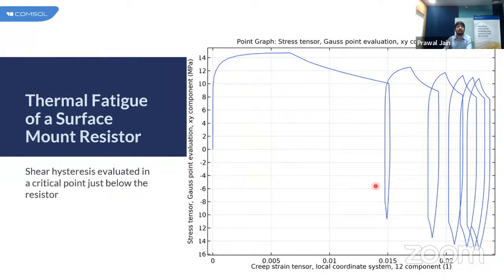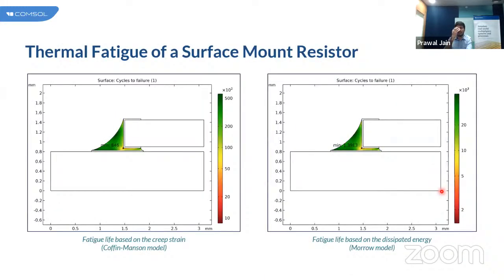And this is the shear hysteresis evaluation at the critical point just below the resistor. We can see the dissipated energy represents a combined contribution of changes in the stresses and strains during a cycle with this shear hysteresis. The temperature cycling can be extended with additional cycles to evaluate whether the state stabilizes further or not. Under some conditions, it may happen that the hysteresis loop is moving in the stress-strain space. So with the last stress cycle that we got, assuming that the consecutive cycles follow the trend and deform less as well as dissipate less energy, the fatigue analysis based on the results of the six cycles gives a fatigue prediction.